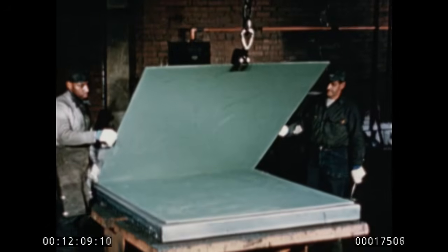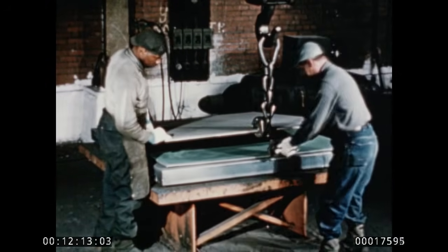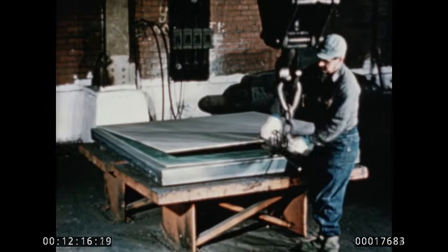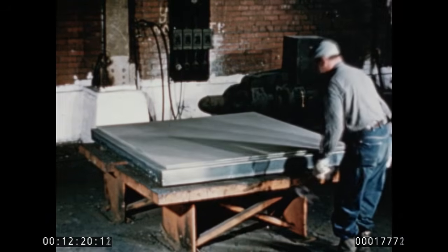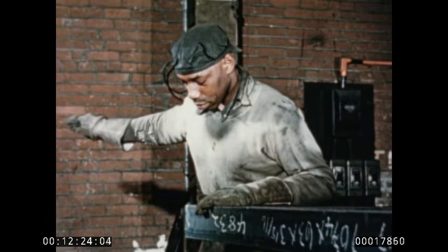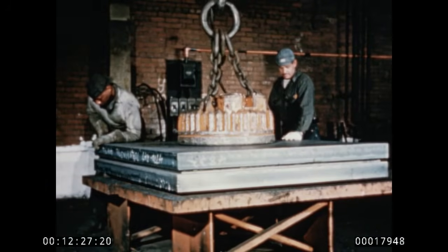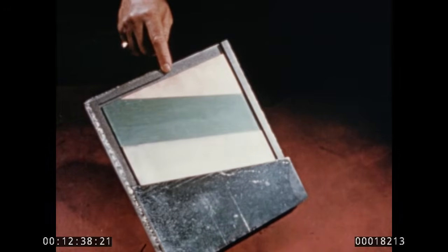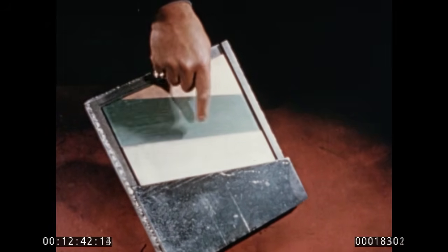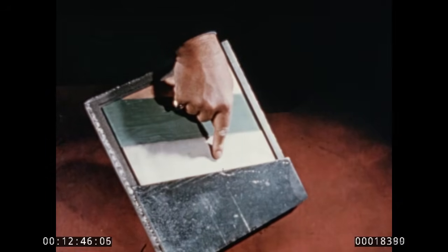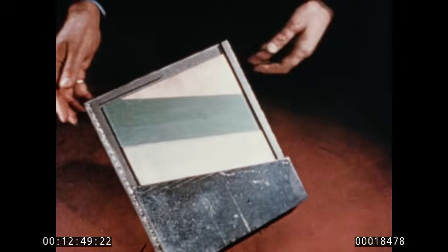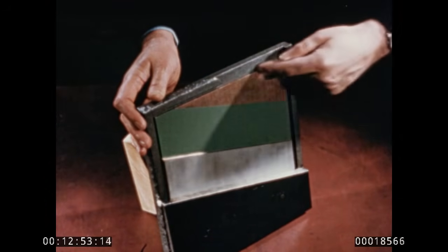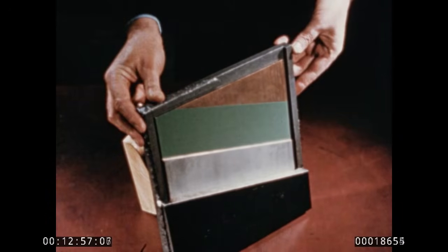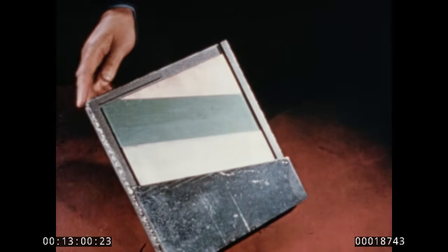The next step is to arrange the alloy plates, separated by a specially developed parting compound, and the steel backing plates into an assembly that we call a sandwich. We make clad steel plates 2 at a time, one on top of the other in the assembly, with the alloy plates inside. You can get a better idea of what an assembly is like from this model. Each assembly is built up of the carbon steel backing plate, then the alloy insert, separated with a parting compound from another alloy slab, and finally, another carbon steel backing slab. The thickness of each layer is carefully computed on the basis of finally desired thickness, assuring uniform thickness of the cladding in the finished plate.